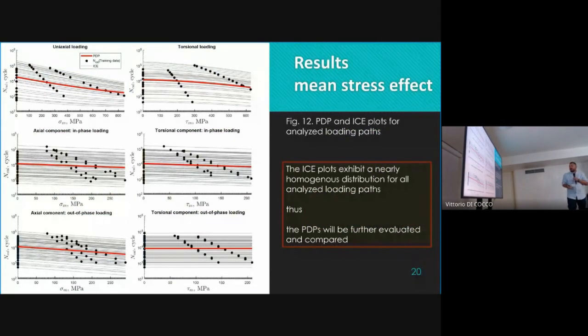So the results for the mean stress, like I said: we have uniaxial loadings, torsional and uniaxial-torsional, then in phase and out of phase, and the impact of sigma m, the actual stress, and the impact of torsional loading mean values. For the uniaxial loading, there is a visible impact of the change of the static stress value. It can be seen on the plot here. It's best to look at the red line. When you go closer to the left, you can see that the line declines, and the predicted fatigue life for the specimen gets lower while we increase the stress. It's also like this in torsional, but it's less important.